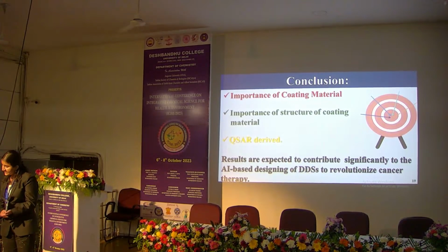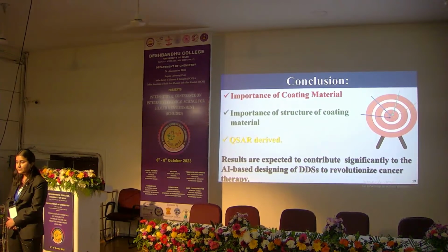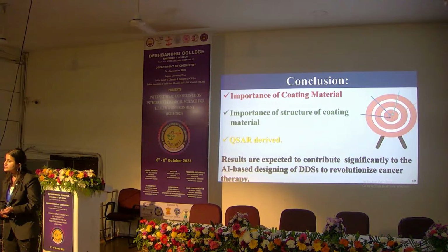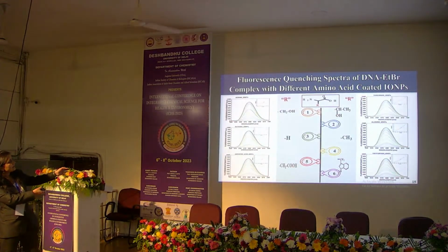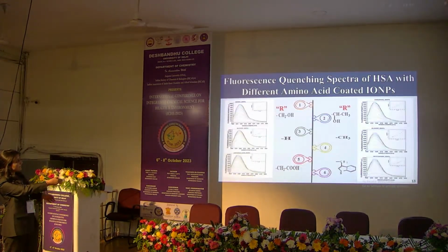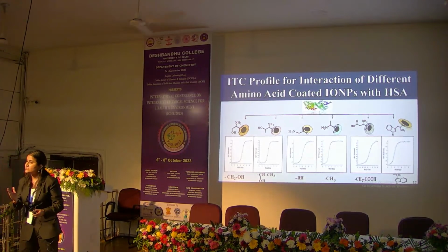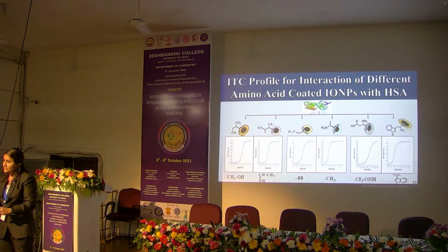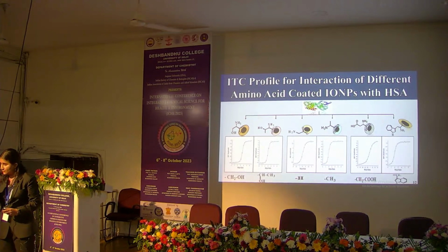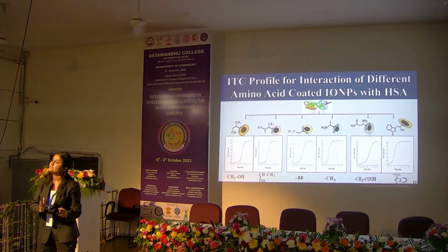Yes, sir. I have performed FTIR spectroscopy. I can show you the spectra of bare iron oxide nanoparticles. There were the characteristic peaks of amino acids also observed in the spectra of amino acid coated nanoformulation, but with a slight shift in their position, which, through the carboxylate group, shows there was a bidentate linkage. The peak observed at around 1700 was present in the amino acid coated formulation, but it was slightly shifted.